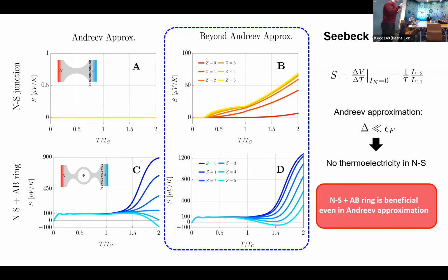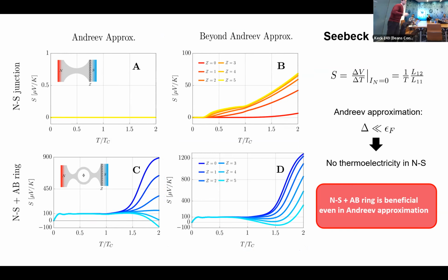And indeed, to understand that, let us focus our attention just on panel A, which, I remind you, corresponds to a normal-superconducting standard Josephson junction without the ring within the Andreev approximation. And as you can see here, the Seebeck coefficient is always equal to 0, independently of the temperature and also for different values of the transparency coefficient.